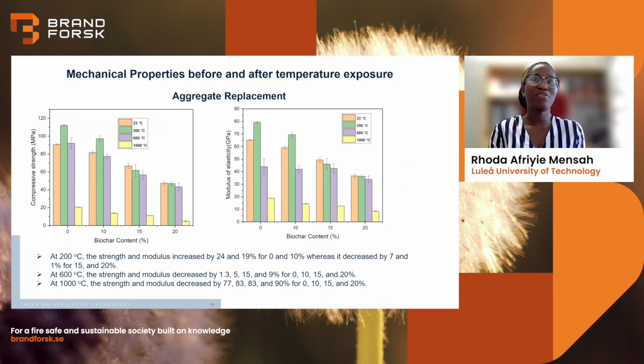So we also have results for the aggregate replacement samples. It has a similar trend as the cement replacement samples, but we saw that the overall reduction in strength in the cement replacement samples was more than that of the aggregate replacement samples. In the aggregate replacement, the cement quantity was constant and we didn't reduce it. But in the cement replacements, the cement was reduced, so that reduced the strength significantly.